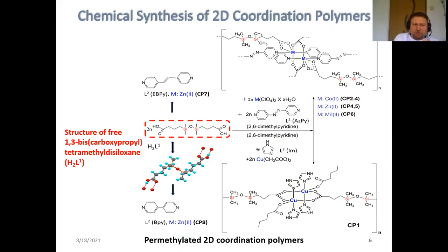The permethylated coordination polymers were synthesized by coordination chemistry of dicarboxylic acid with a tetramethyl disiloxane spacer as a reticular anionic crosslinker, marked here as H2L1, in combination with a nitrogen heterocyclic compound as neutral ligand, marked as L2, for several transition metals from metal salts marked as MX.